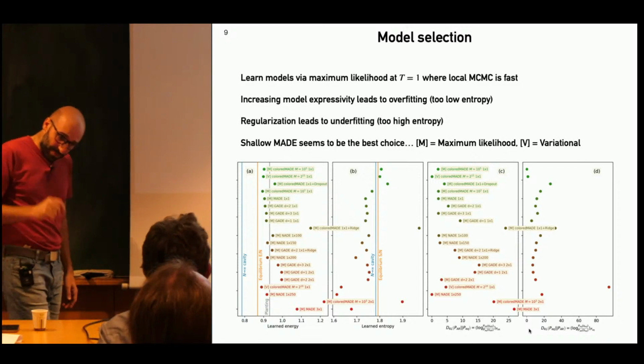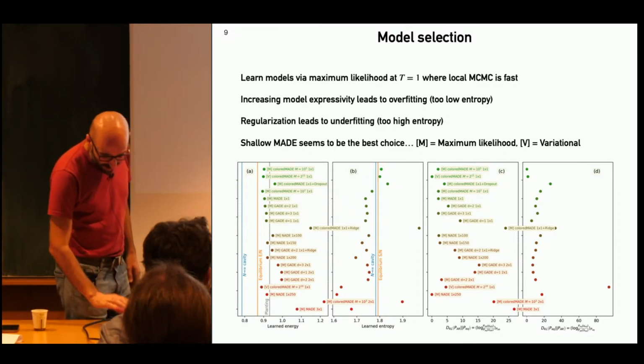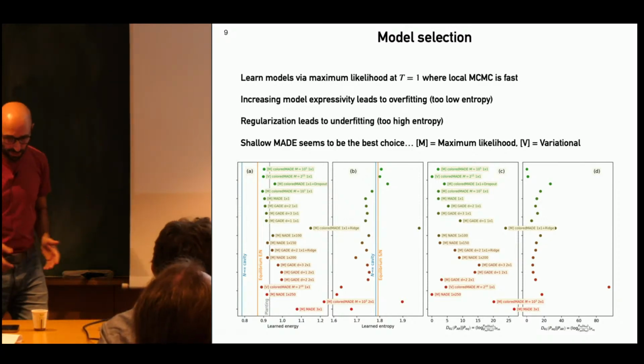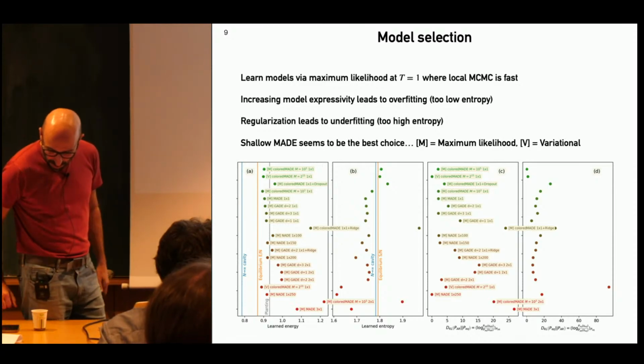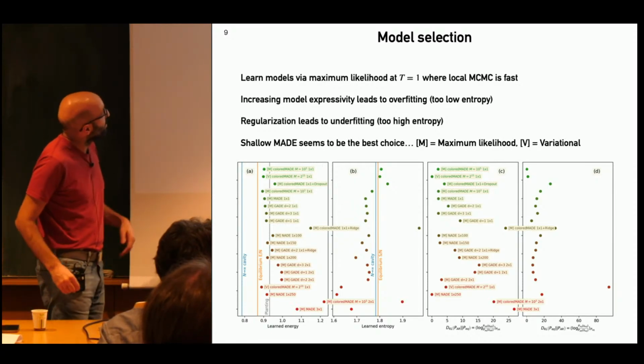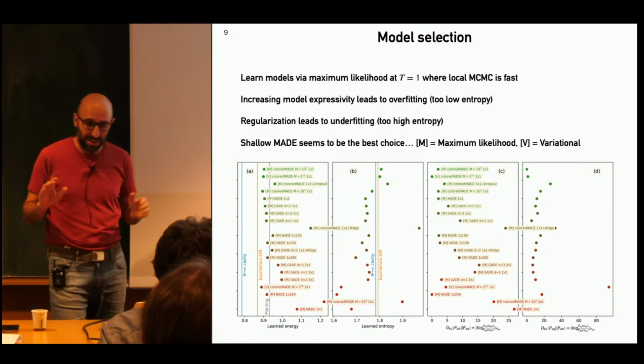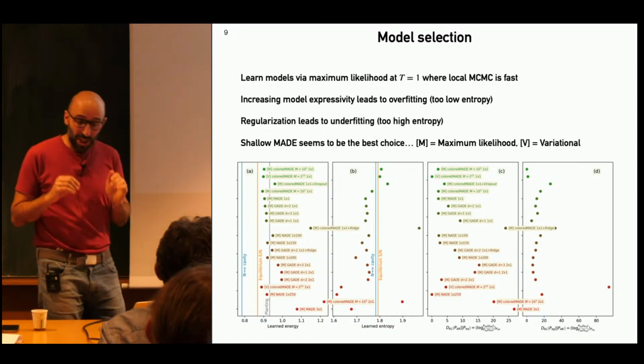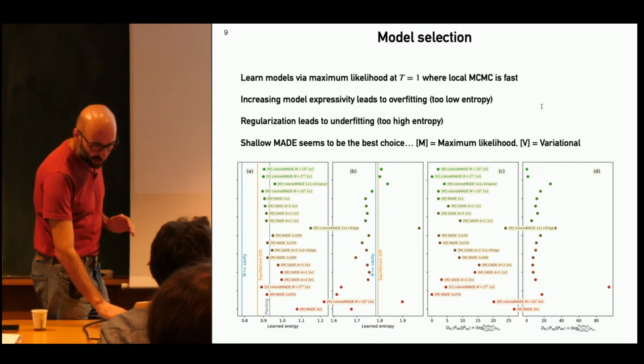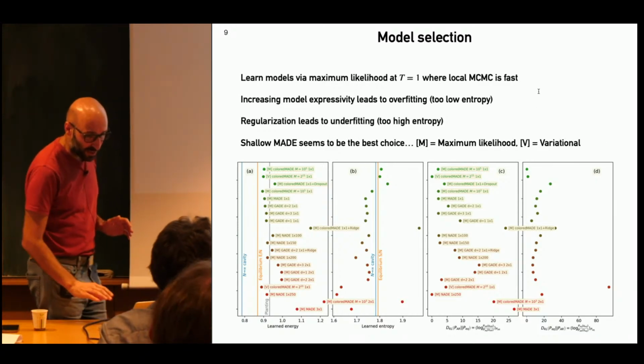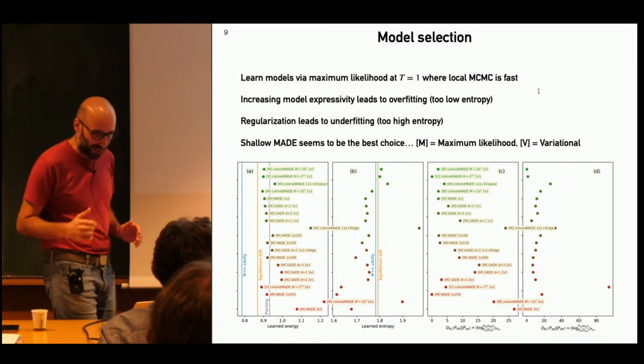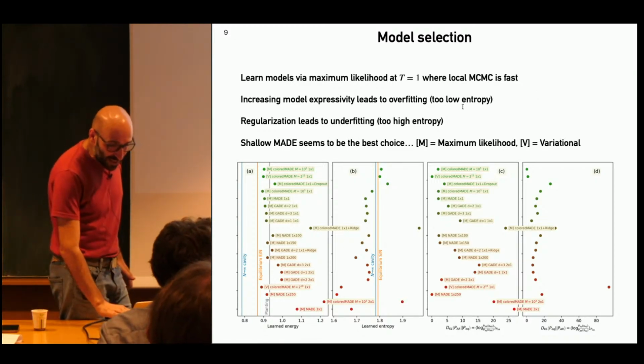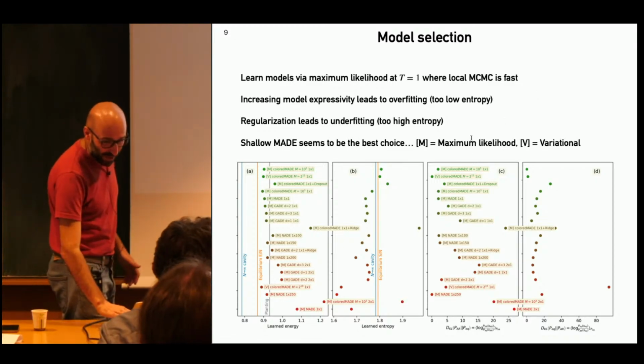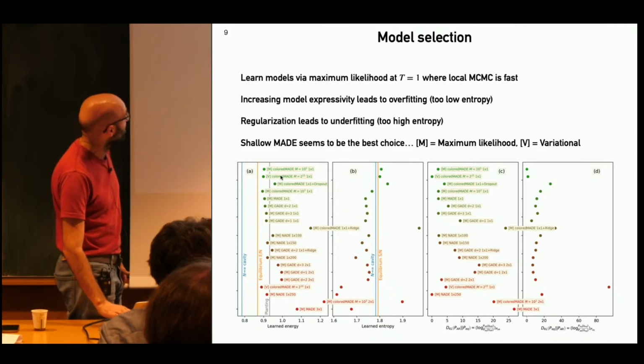Now the first step was, we want to repeat the same thing that we did for the spin glass. So the first step is to select a model. What we did is to take temperature 1. We generate a sample from local Monte Carlo, which is fast at this temperature. Remember that the glass transition is at 0.17. And then we considered many different architectures.